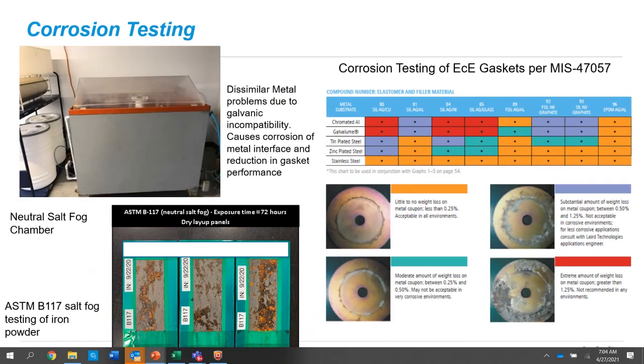So in my experience, the two biggest problems we run into are exposure to fluids and then corrosion. Corrosion really across the board, everything corrodes, almost no matter what it is. So two different areas, there's standard testing for it. You're looking at, in the upper left-hand corner, a salt fog chamber. Basically what you create is a warm fog atmosphere of a saline solution, which you then immerse the material in. It could be by itself, it could be in situ with something else. So there's a couple different ways to test it.